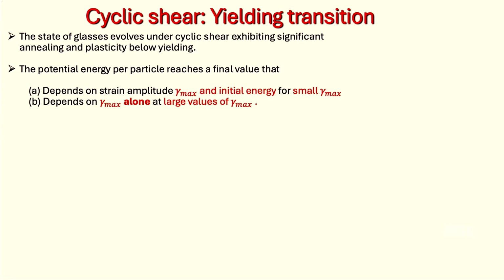So this is one set of results for athermal quasi-static shear, where basically the summary of what I'm going to show you in steps is that the energy per particle of the system, which is the quantity that we monitor, depends on the strain amplitude and the initial energy when I apply small amplitudes of shear. But for sufficiently large amplitudes of shear, the amplitude by itself determines the final state that I reach. And in between these two regimes, one has the phenomenon of yielding, okay?